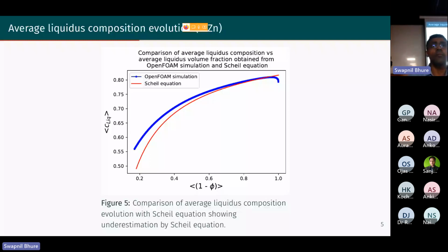And you can see that the estimates are fairly consistent with what the Scheil is, as you expect, but there are certain important differences, particularly with how it approaches the zero liquid fraction, and those are relevant for the final compositions during the last stage of solidification, which might be relevant for the future precipitates or future phases that might form post solidification. So those differences might become important, and therefore it's important to highlight them in contrast to what you get initially.